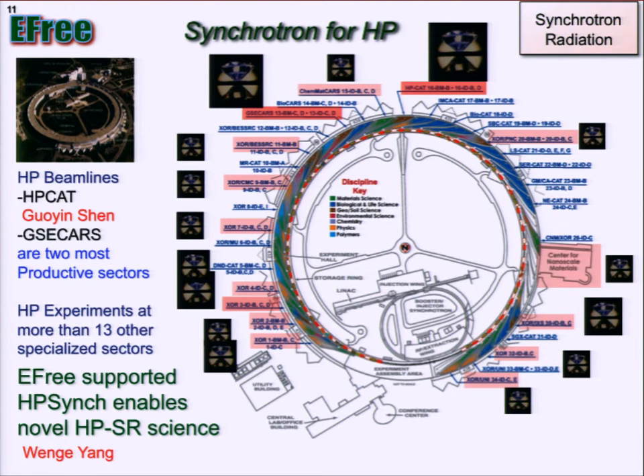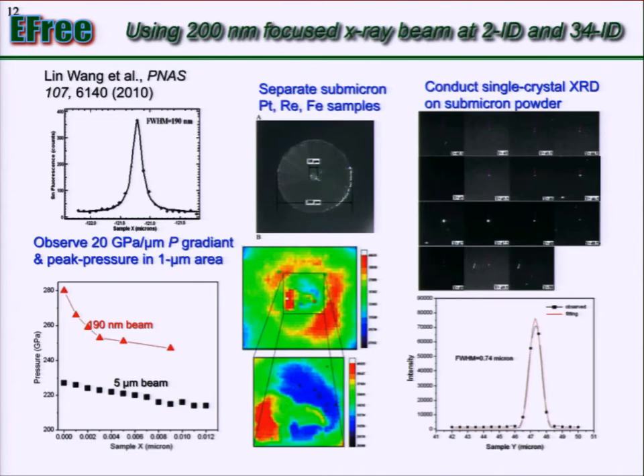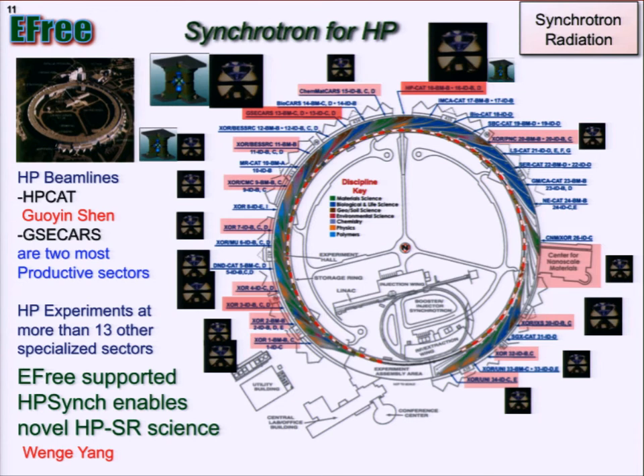This is also meV, but a small m, energy resolution. And some of these can get very high energy X-ray, in this case several hundred keV. Some have a better way of doing a very small spot, like they can get to 10 nanometer resolution. So we cannot build everything in one sector, because then you make it too complicated and you cannot do anything well. So here most of the study we use this beamline for the most routine study, but for special study you use all the different beamlines at a single time. This is also a program supported by CDAC and NNSA called HP Sync. This is to reach out for all that.